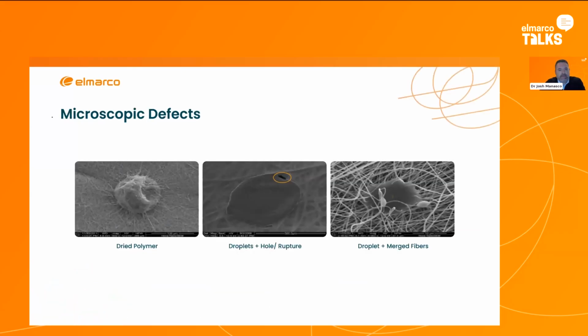And these are some of the examples of the microscopic defects that can form. The reason these are important, if you're talking about a hydrophobic membrane where you're trying to block the water from penetrating the membrane, or a high quality air filtration material like a HEPA material, or liquid filtration where you're trying to have a certain log reduction of bacteria, for instance, is that these holes can be generated from these defects, either because they have different mechanical properties than the rest of the web, or because they form some hole whenever there's shrinkage from evaporation of the solvent, for instance, that can cause holes.